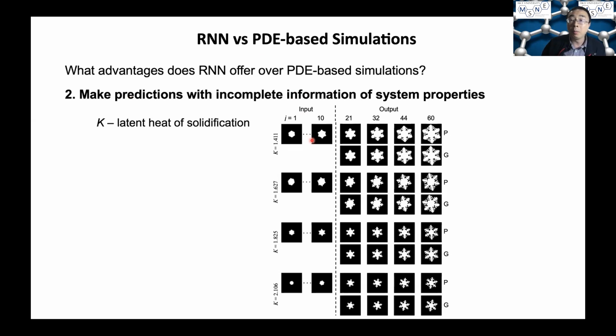But in the machine learning approach, if you feed the image sequence into the model, then it's possible for the model to infer the material properties from the image sequence, and then apply such knowledge to implicitly infer the material properties and predict the evolution process. So here, for example, in the dendrite growth example, we train the model with dendrite growth simulation using different latent heat parameters of the system, right? And after training, we feed the model with a dendrite growth sequence generated by a latent heat value which the machine learning model has no knowledge about, right? So it doesn't know explicitly what the latent heat is for the imaging sequence we put into the model. But the model is able to sense this parameter value from the input frames, and then correctly predict the evolution trajectory based on the input.